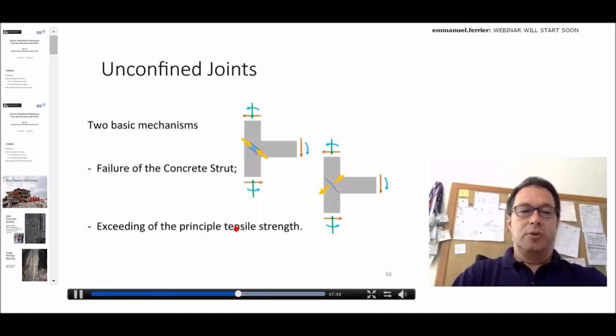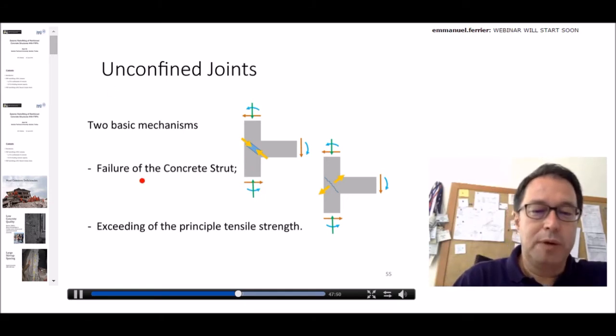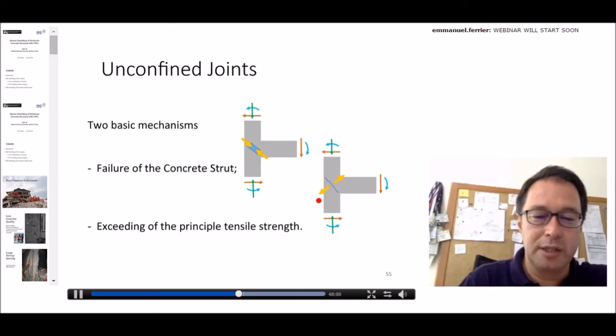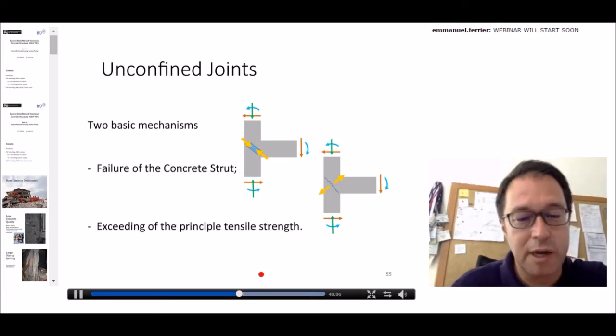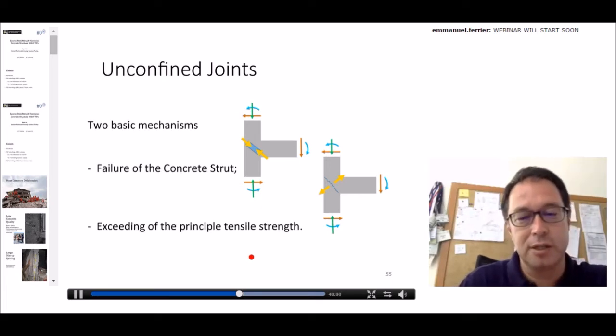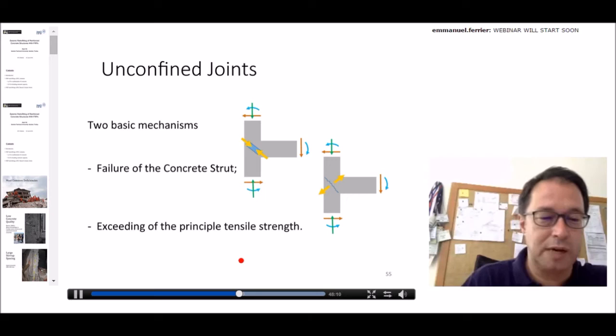So for the joints, we could say that we have mainly two mechanisms: either the failure of the concrete strut in compression, or the exceeding of the diagonal tensile strength of concrete within the joint, if you don't have joint transverse bars. And this is the case we are examining, because we have a lot of this kind of structures.